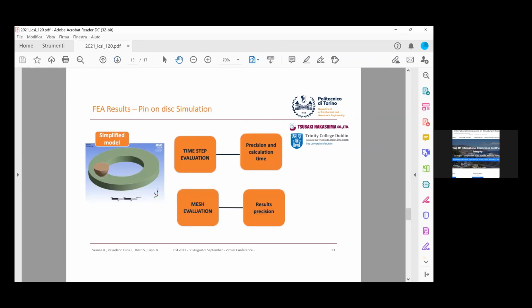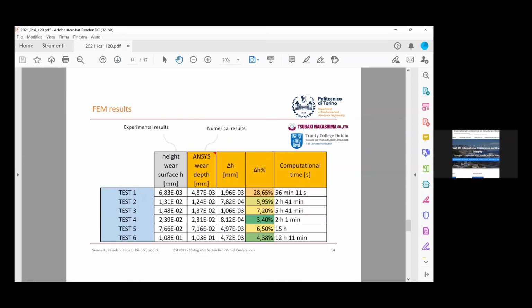Then a simplified and linear model was developed, and we focused on the time step and the mesh evaluation. In fact, a good time step value is given by the trade-off between precision and calculation time. Moreover, a too coarse mesh can lead to a worsening of the results. In this slide, we have the comparison between the experimental and numerical results. The percentage difference of wear depth between the pin on disc test and the ANSYS simulation is always lower than 8%, except for test 1, where the computational time is low, less than 1 hour.